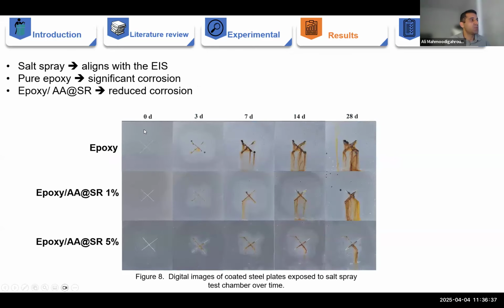In salt spray test, we applied the coating on steel plates, and we intentionally produced a damage on the surface of the coatings. And we placed the samples in salt spray chamber, where the samples are continuously exposed to a fine mist of salt water. And we visually investigated the corrosion products on the surface of samples over time. After 28 days of exposure, we observed a lot of rust on the surface of control sample. And after adding 1 and 5% of smart nano reservoir, the amount of rust was decreased.